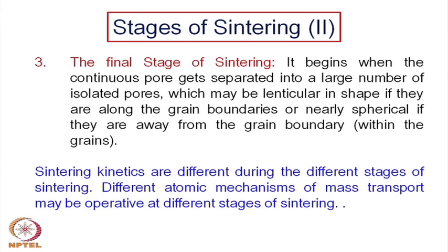So, the pore is no longer a continuous phase, the solid remains continuous, but the pores become isolated, and the shapes of individual pores depend on where exactly they are located. They may be located at the grain boundaries, at the contact area between the two grains or the two particles, or they may come within the grains.